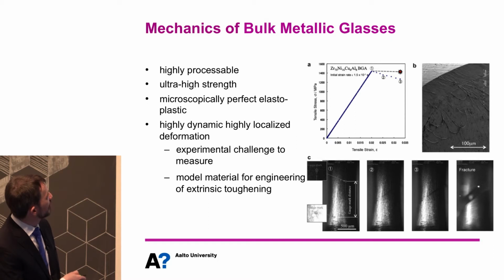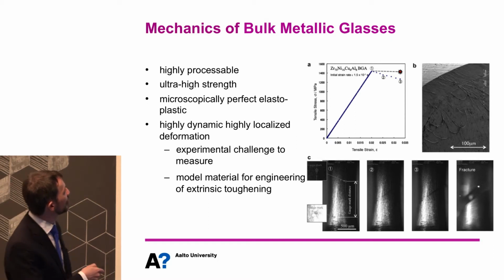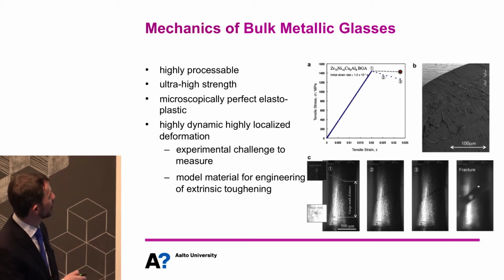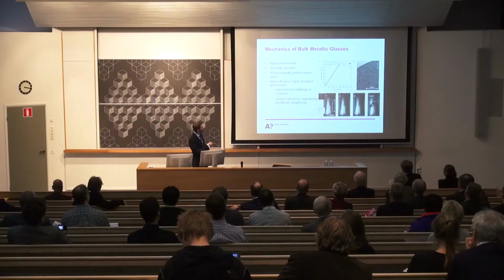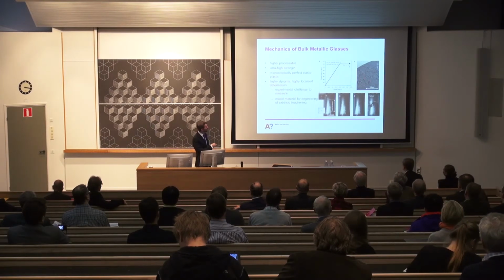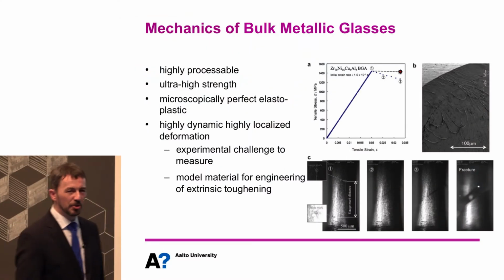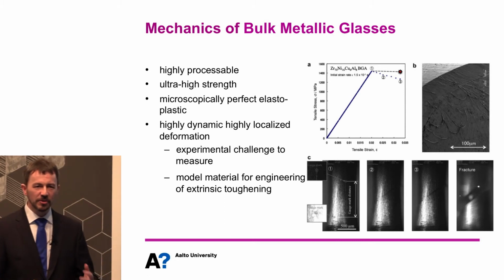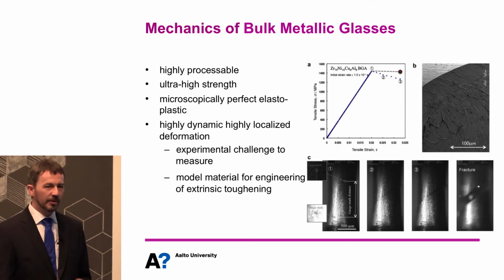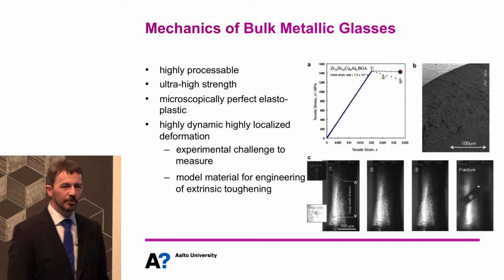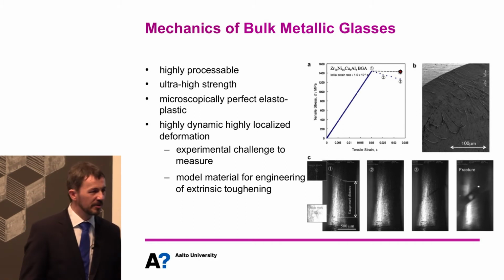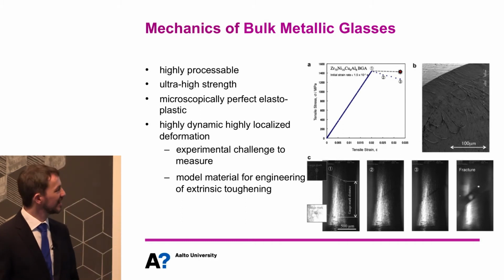So here's a more scientific plot, perhaps, of the mechanics of zirconium-based glass-forming alloys. You can see that it just has this elastic region, and then it's perfectly plastic. Microscopically, these things are perfectly plastic. And on the fracture surface, you can see that they actually melted again. So microscopically, this material has all the toughness you could like. It absorbs enough energy to raise the temperature of the material above the melting point of the material. You cannot have more toughness than that.